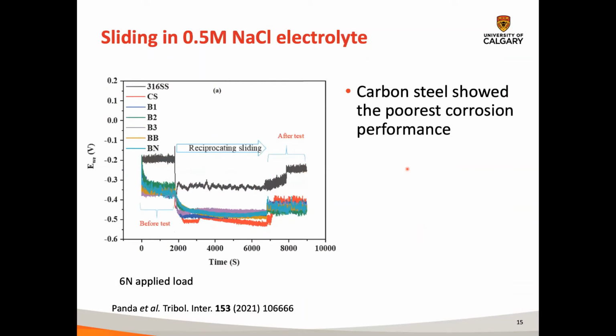What we did then is we put these samples in the corrosive medium. So in this case, we looked at 0.5 molar sodium chloride in deionized water. And what this graph shows you is at the beginning, this is before we start moving the tribometer, and then all of a sudden we start sliding the experiment back and forth. And we see a change in the working electrode potential that we measure in our 3 probe measurements.